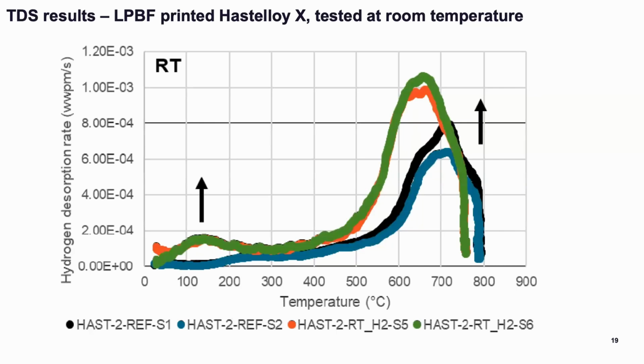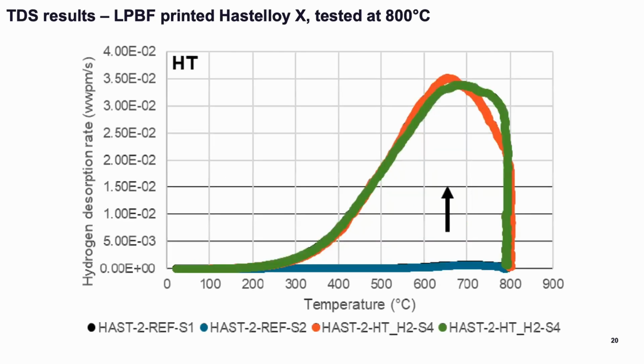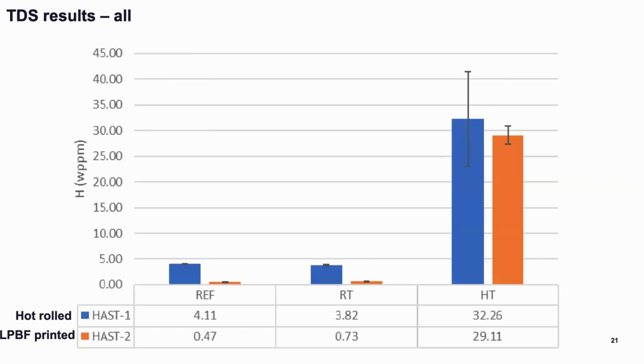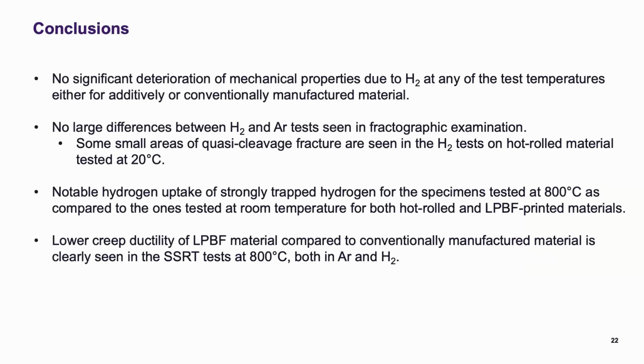For the printed Hastelloy X tested at room temperature, we detect some hydrogen uptake. The reference concentration is lower than for the wrought material. And maybe we detect some uptake, and also maybe a shift to weaker trap sites. And this is the overview. I think it says basically the same as what I just said.